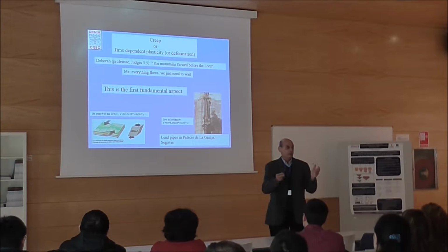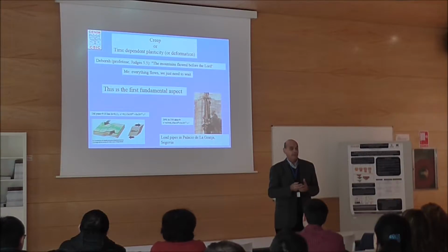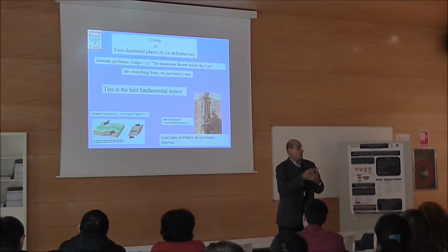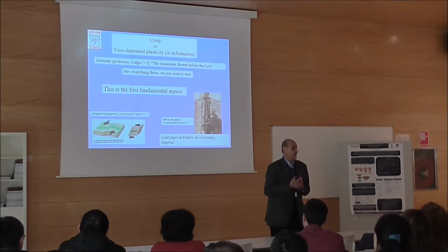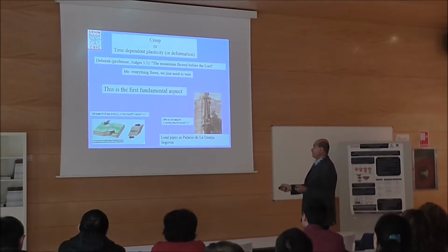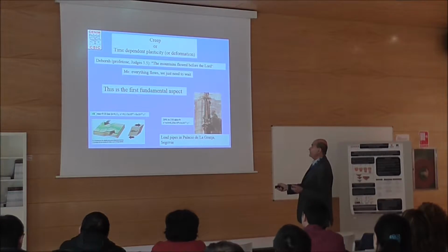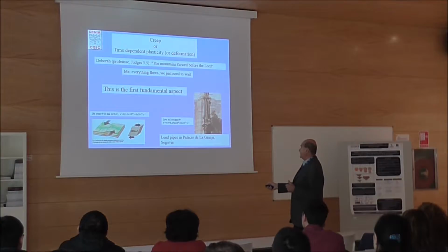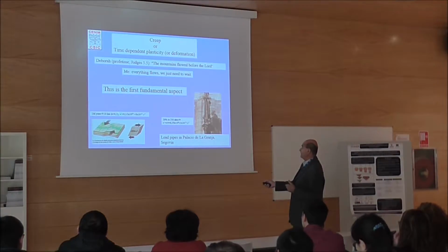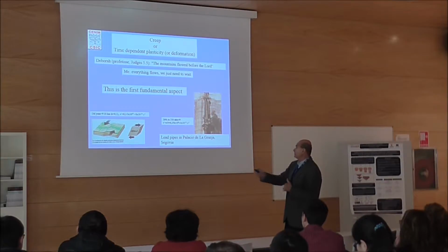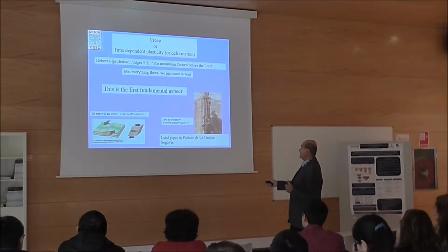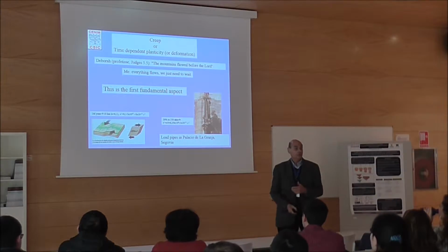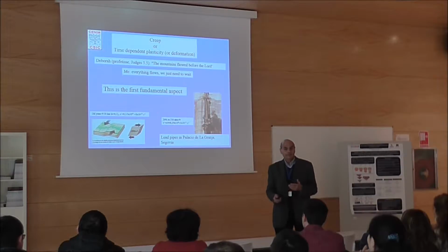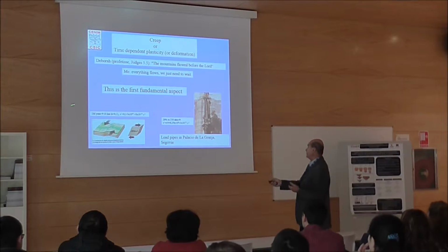Because for one thing, every 3 papers on creep, they put in a threshold stress function. Threshold means no creep. And I don't believe in that. And it's very difficult to demonstrate because we don't want to wait. For instance, in geological matters, if you have 1 million years, there are mountains that have been shifted by shear stresses, and we will have about 10 kilometers distance from one part of the mountain to the other, and in 1 million years you will have a strain rate of 10 to the minus 15 seconds minus 1. 10 to the minus 15 seconds minus 1 means a lot of time. A lot of time, millions of years.